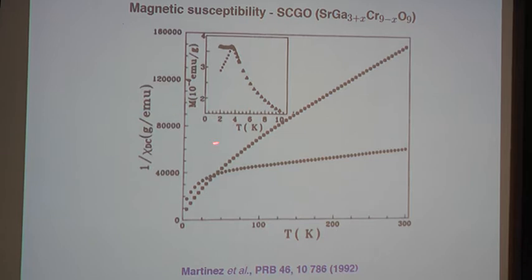And in fact, if you zoom in at low temperatures, then there's some indication of spin glass behavior, but on a temperature scale of around 4 Kelvin—in other words, something like 1/100th of the basic interaction scale in the system. So there we have a consequence of the degeneracy that I was talking about with the toy example: we have fluctuations destabilizing an ordered state.